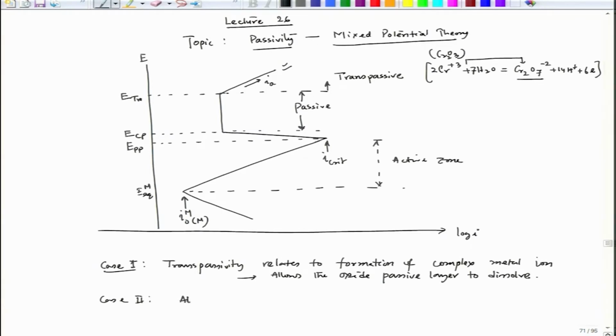Let us say in case of aluminum, if we increase the potential further, the plot can be like, let me pinpoint those points, this is A, B, C, D, E. I am not using E because E is expressed as potential, so I can mention as F, then this is G, H. So, if I go in case of aluminum or titanium, further positive potential, if we take forcefully that metal to a positive polarization, if we allow that anodic polarization to take place, the polarization line can go A, B, C, D, G and H.